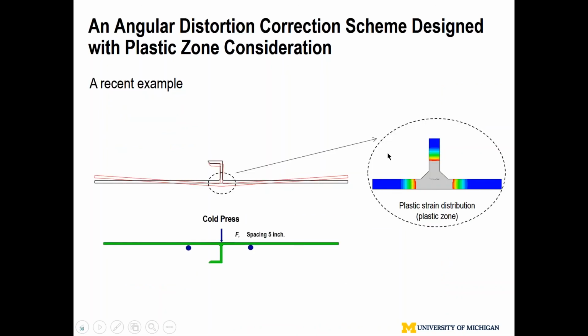But to illustrate that, say for this particular stiffened panel, the plastic zone is in this neighborhood, about a couple times the fillet size. That means as long as I clamp this regime, okay, that will be most desirable. But obviously too close, you're going to interfere with the welding. That means the question is how far away I can clamp without interfering with welding. So for this research, we did some quick calculation. We found we can do 5 inches spacing and still hold this area.